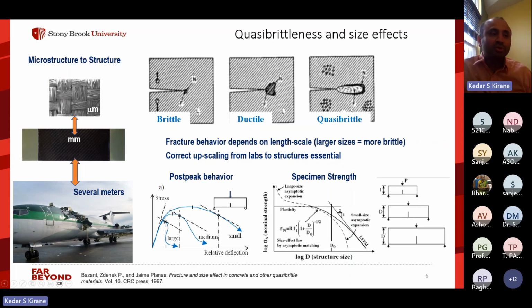But what happens because of the process zone is that the scaling deviates from this straight line. And this deviation is actually described by this empirical law, which is called the size effect law, which was first developed by Professor Bazant, who was also my PhD advisor. And this is the well-known form of the size effect law, where sigma_n is the nominal strength of the specimen, and D is the size of the specimen. And it has two constants. One is sigma_0, which kind of represents the strength at zero size, like when D goes to 0. And then D_0 is like a length scale parameter, which is related to the size of the FPZ. So when you have a non-negligible FPZ or process zone, you have this kind of transitional behavior of the strength size effect. And when the specimen size becomes really small, this size effect vanishes.